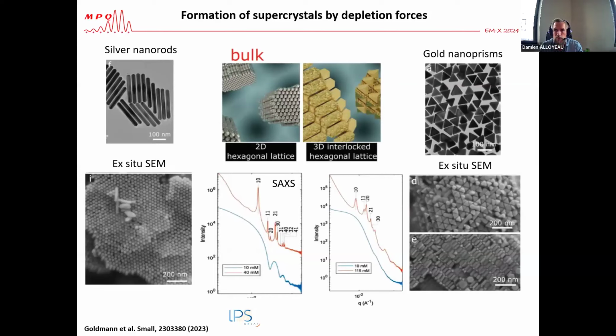try to study the formation of supercrystals by depletion forces using the same silver nanorods and other nanoparticles, which were gold nanoprisms. So depletion forces are an attractive force that can be controlled by the concentration and the size of micelles inside your reaction media. When you increase the concentration of CTAC, which my colleagues are using, you start to see this pattern on your SAXS curves that describe the formation, in the case of silver nanorods, of a 2D hexagonal lattice, and you can confirm that by doing SEM. And when you work with the nanoprisms, the nanoprisms form a 3D interlocked hexagonal lattice, but also confirmed